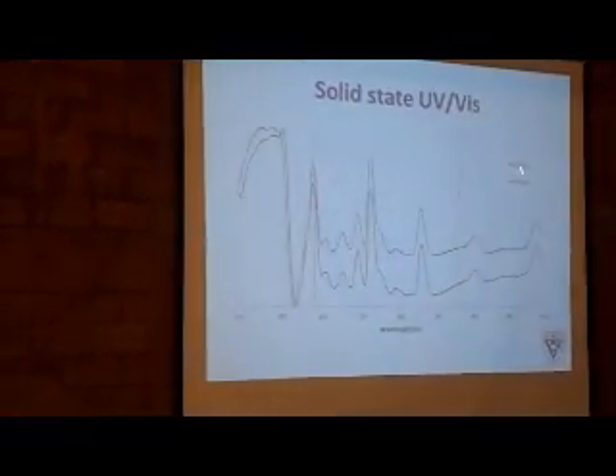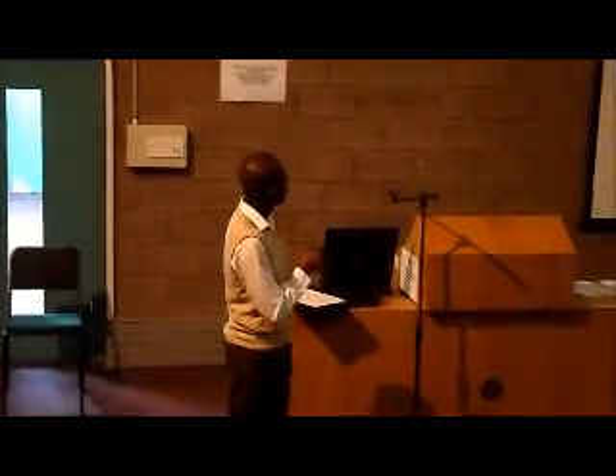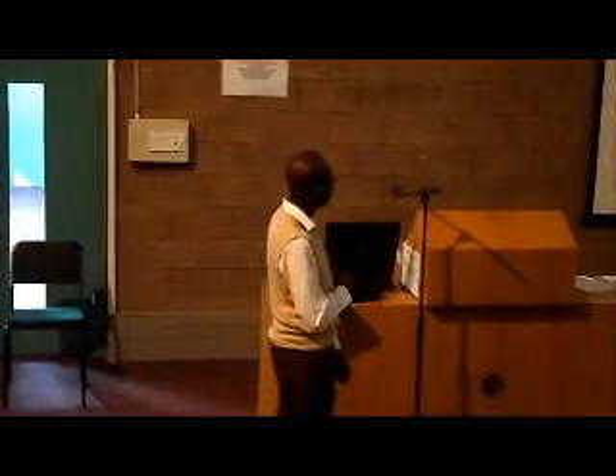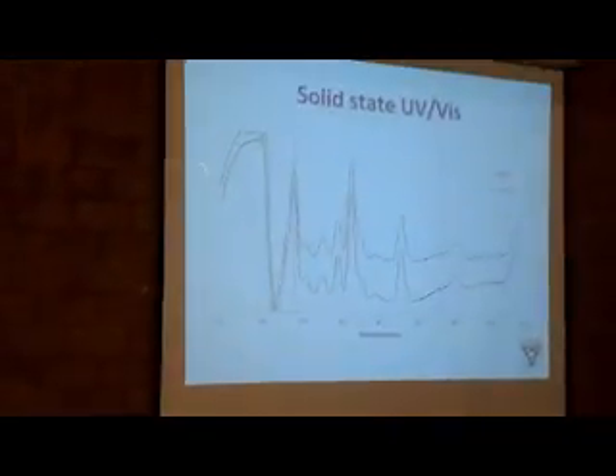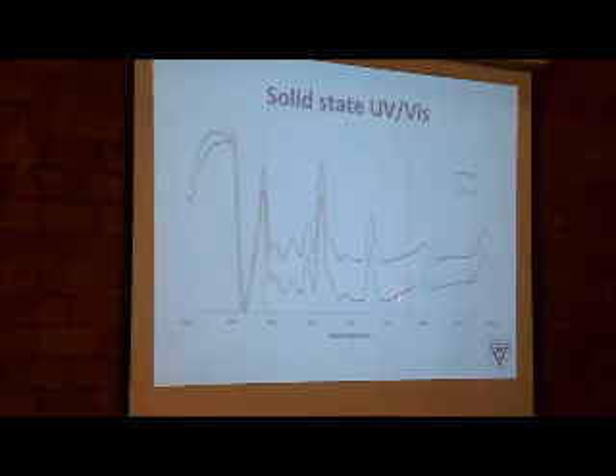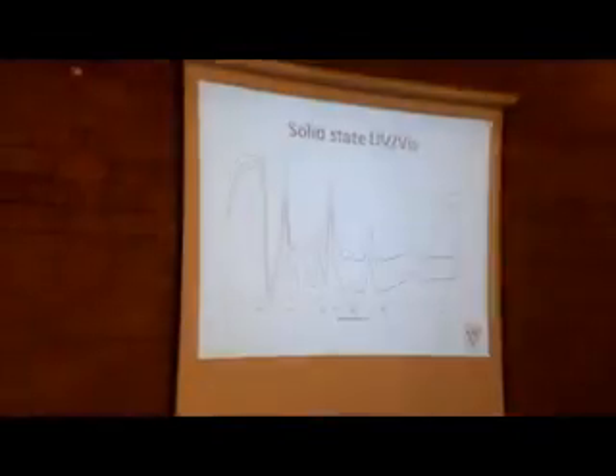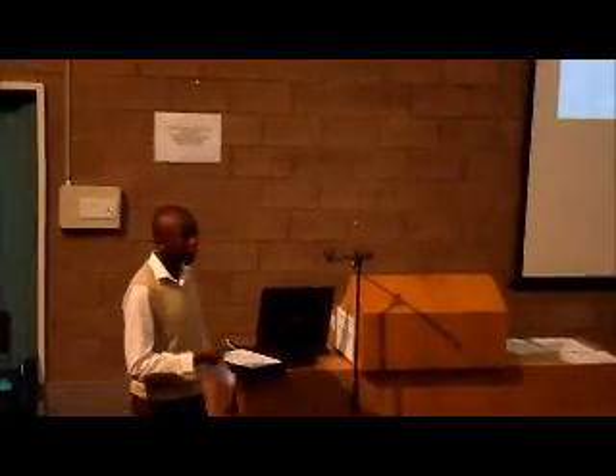Now just to move on to the solid state UV-vis, I decided not to include the intensities because those are irrelevant due to the fact that this is a solid state study. Now you can see that I've compared erbium product 2 to erbium product 1. As you can see from the peak intensities and the peak positions, these structures are pretty much isostructural. So for the rest of the talk, we can just bunch them together and say that these compounds are isostructural. This is the UV region, the visible region, and the IR region. And it was quite great to see that we had quite a bit of absorbance in the visible region, which is of great importance as we wish to observe fluorescence in the visible region for easy detection.